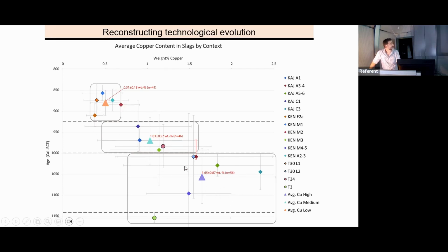And you can see a general trend of improvement in the efficiency of the smelting process, right? From an average of about 1.65% copper to an average of 0.5%. So there was an improvement in the technology all the time based on different mixtures of flux and ore and charcoal, et cetera. But we also see that the transition between this period and this one is very sharp, especially in the standard deviation. You see the standard deviation here, it's much, much smaller. So they suddenly started, in the most efficient technology, following a very specific smelting protocol that was very identical from one smelt to the other.